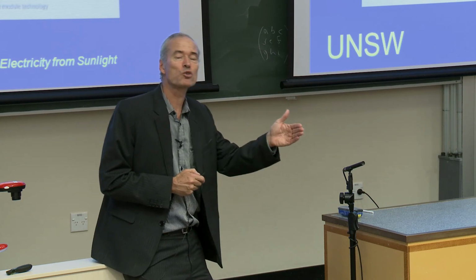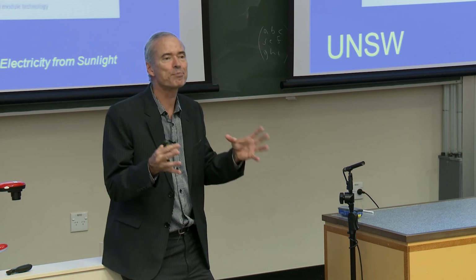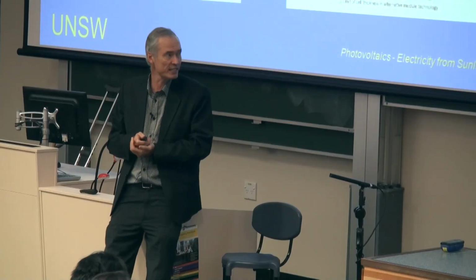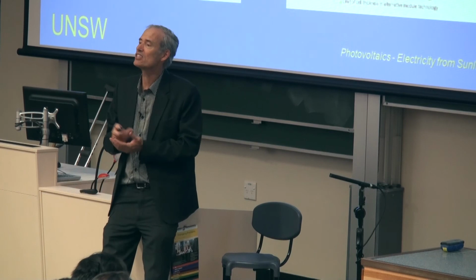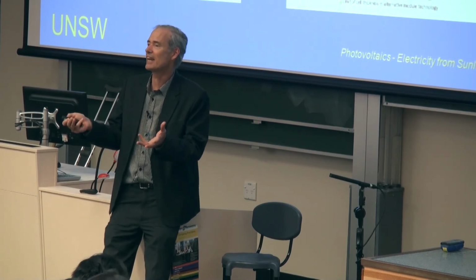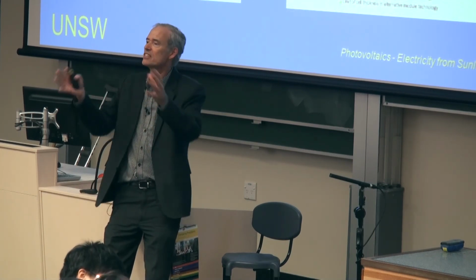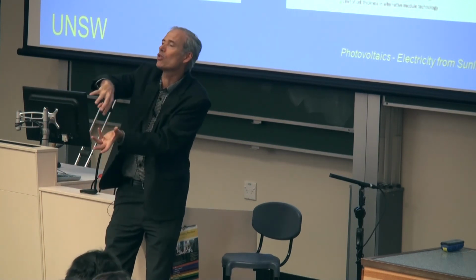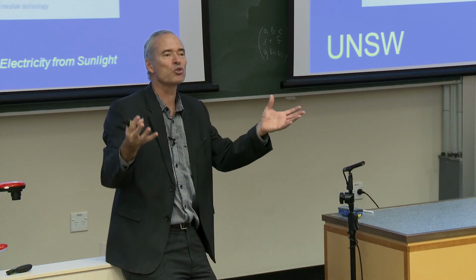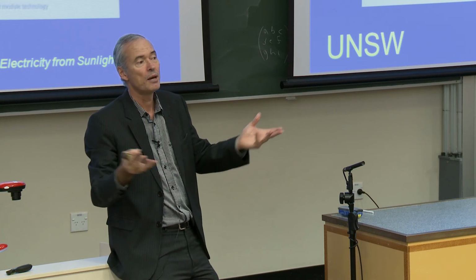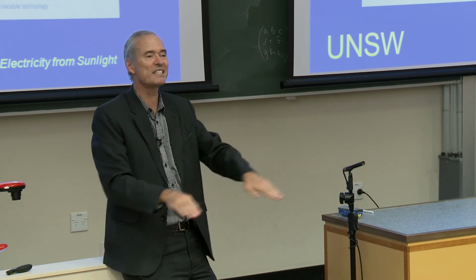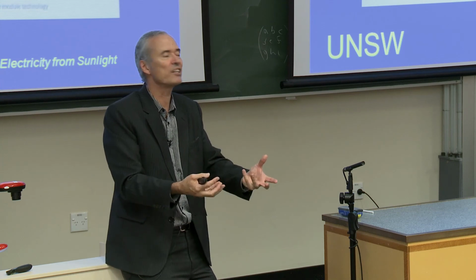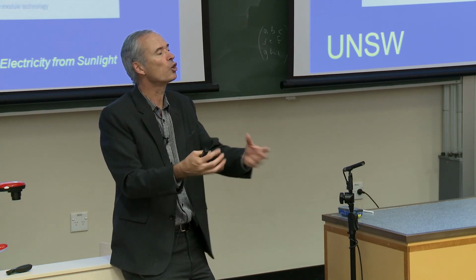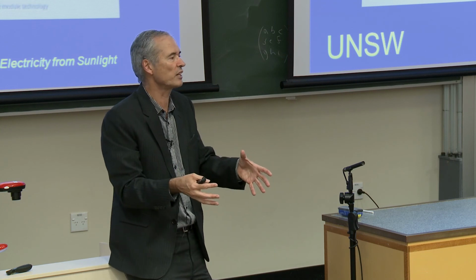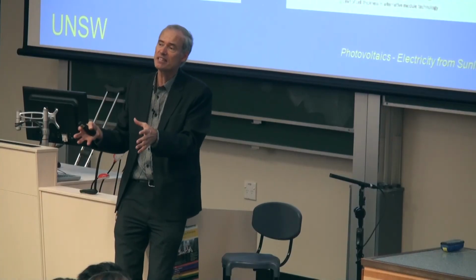In the last 2 years, when I've talked about the casting process used for making multicrystalline silicon, I've talked a lot about this new technology called seeded casting. It's still a casting process where you simply pour the molten silicon into a mould, let it cool slowly, and therefore it crystallises. But with seeded casting, you put a seed layer at the bottom to nucleate the growth of your crystals to try and cause the ingot to grow as a single crystal silicon. And there's been some success with it, but there's also been some problems with it.